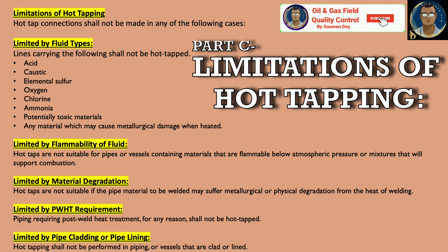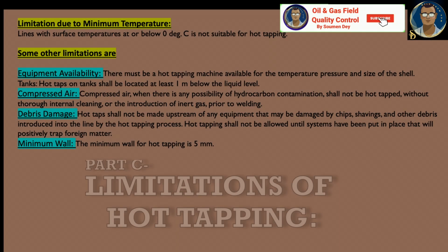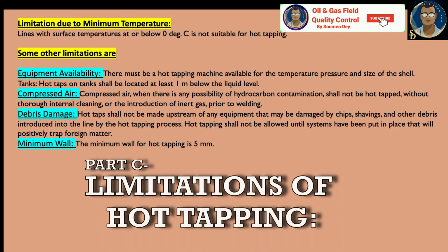Limited by pipe cladding or pipe lining. Hot tapping shall not be performed on piping or vessels that are clad or lined. Limitation due to minimum temperature. Lines with surface temperature at or below 0 degrees centigrade are not suitable for hot tap.